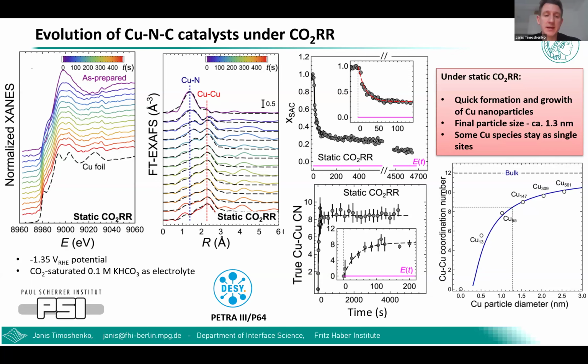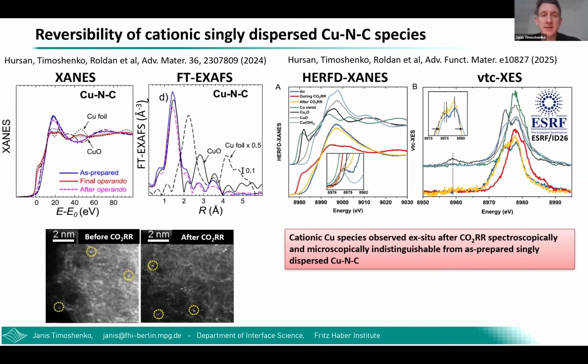But perhaps the most exciting or intriguing property of this catalyst is that this transformation into metallic particles is completely reversible. So as soon as you remove the applied potential, the catalyst actually reverts back. So these metallic copper clusters are gone. And this was initially very confusing because you can make a microscopy image of the catalyst before and after the reaction, and in both cases you see that there are again only single atoms present. You don't see any of these metallic nanoparticles which you saw in the in situ and operando investigations.